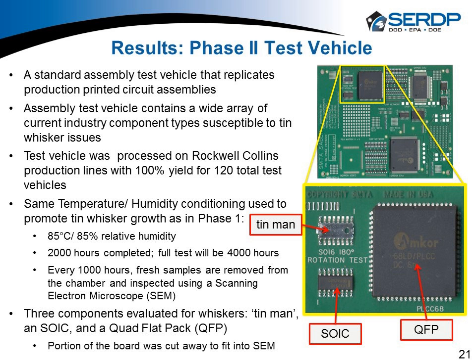So for this part, we built the boards. We had 100% yield. We built 120 test vehicles. And then we carefully came out. We had these routed so you could snap them out of here, and that became our test vehicle for phase two. And in phase two, we did the same thing, 85-85. We did the full 4,000 hours. But in this case, we pulled things every 1,000 hours rather than every 500 hours, and we did not do two different sets. We just put everything in, and after one set had accumulated 1,000 hours, we pulled it out, never to go back in. The next set accumulated 2,000 hours, we pulled that out.